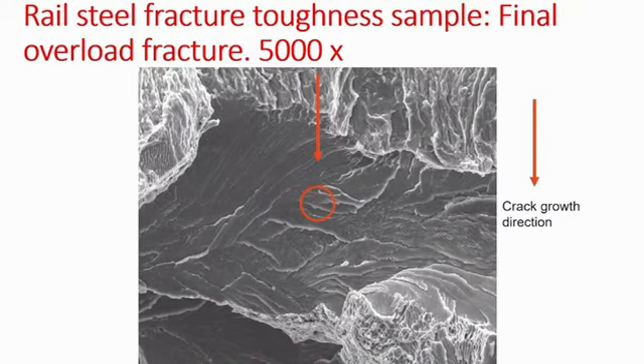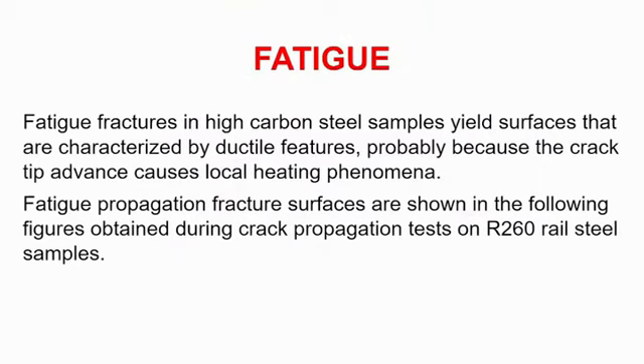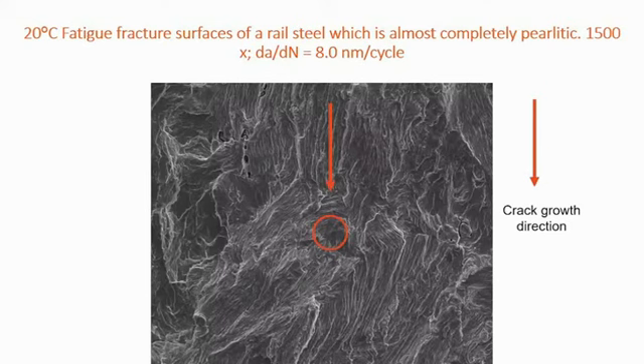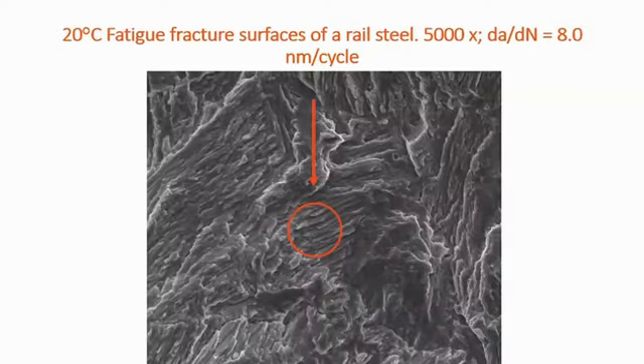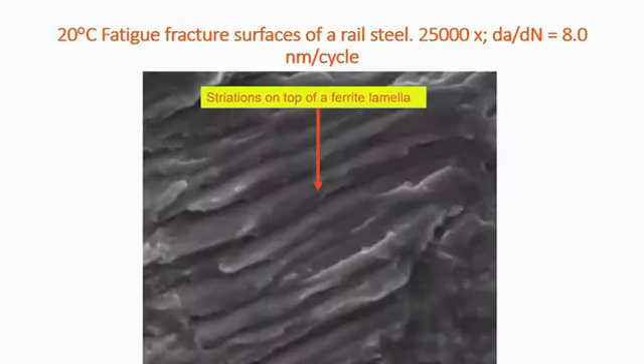Very brittle. But if you have fatigue, then something happens. This is the fatigue. And for sure, this is not a very brittle surface. And as you increase magnification, you can see that again, in a different way, ferrite crystals stand out from the bottom. And if you look at very high magnification, you can even see striations on top of a ferrite lamella.